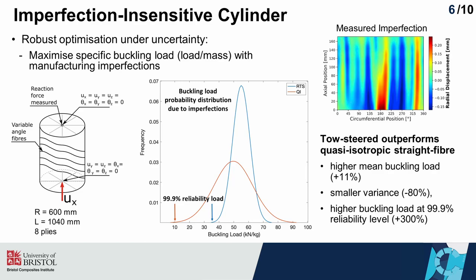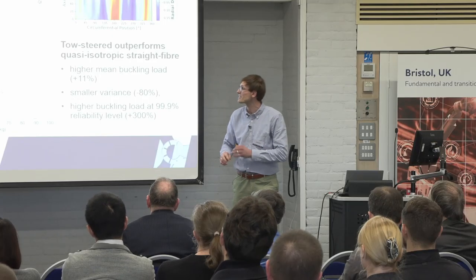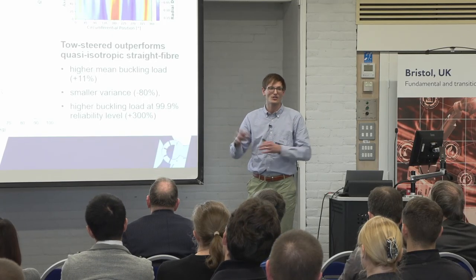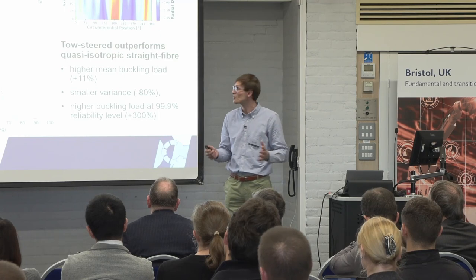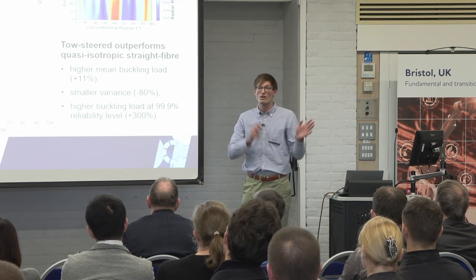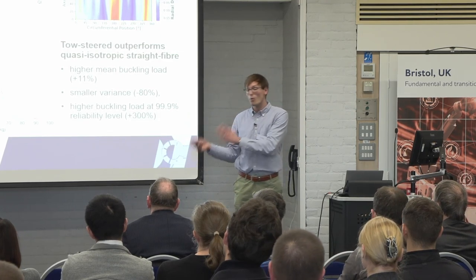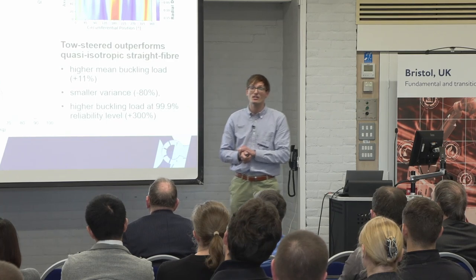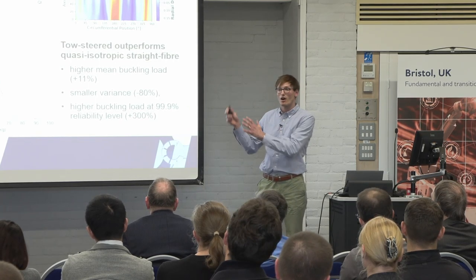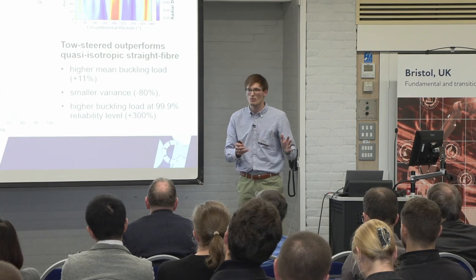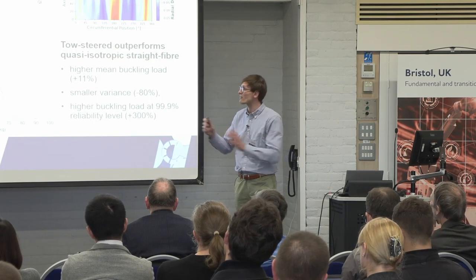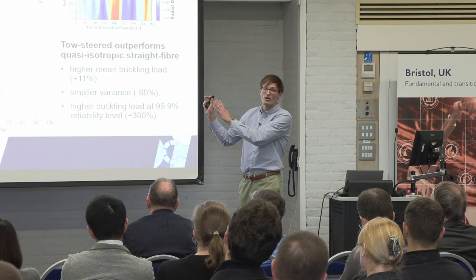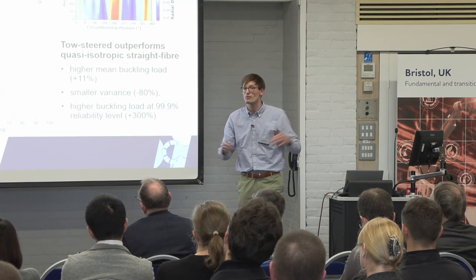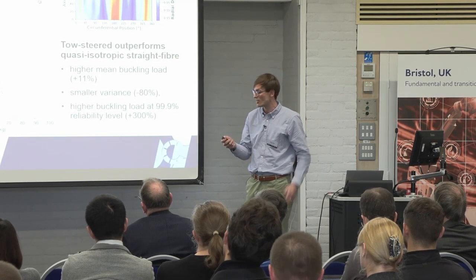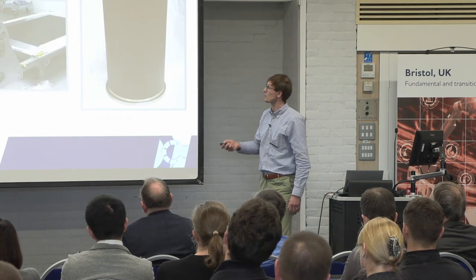Now, unfortunately, this was a year and a half project, so we couldn't actually manufacture tens of these cylinders. We also didn't have the funds to do so. So what we did is we manufactured one of each, one QI cylinder and one of these rapid tow shear cylinders to demonstrate that our models actually correlate with experiments. And if they do, then we have some confidence that what we see here actually reflects what we would see if we had the money to manufacture tens and tens of these cylinders. And so that's basically what we did.